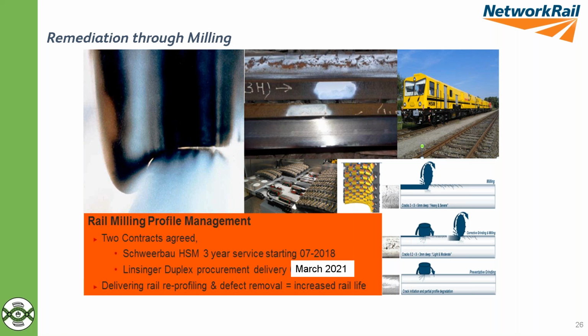Some of the new things we might be able to do to reduce some of the surface damage and actually remove it. So we've had some successes where we've been able to mill, remove the cracking up to 5 millimeters deep, effectively produced a rail then free of RCF cracks with a very good profile, and then effectively, rather than changing the rail just because we've got some surface cracking in the top 5 millimeters.